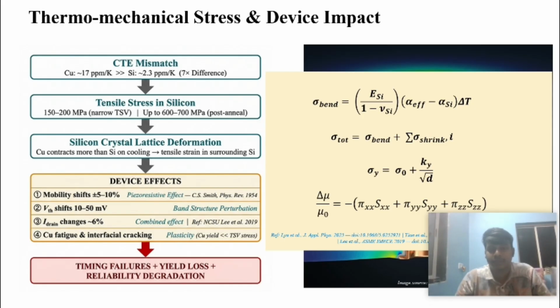And the fourth equation is mobility change due to the piezoresistive effect, where pi is the piezoresistive constant and s is the stress generated in particular directions. So this all will lead to timing failures, yield loss, and reliability degradation in our silicon wafer.